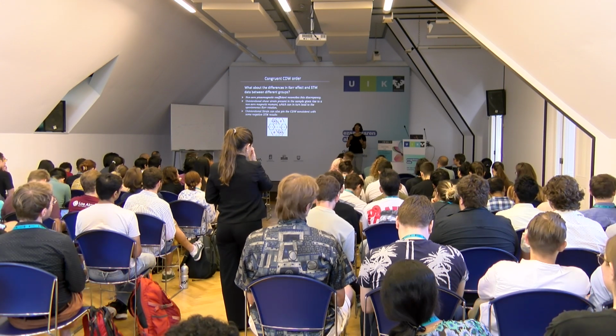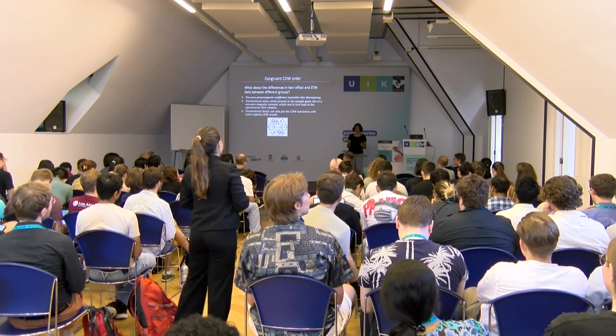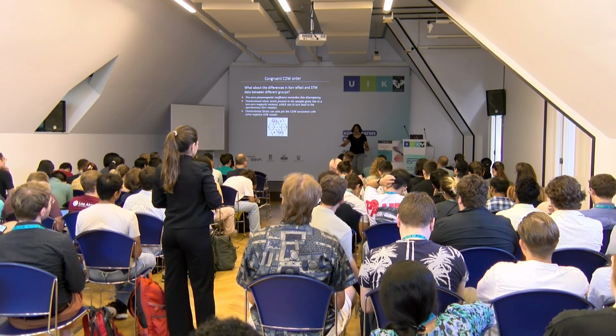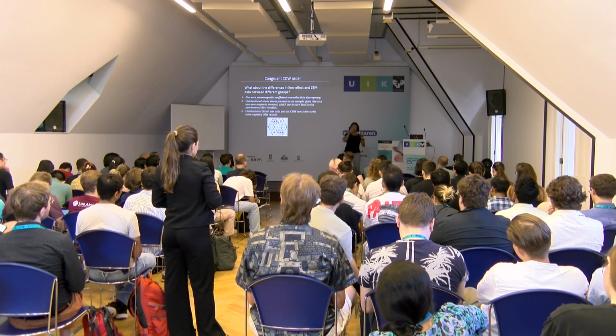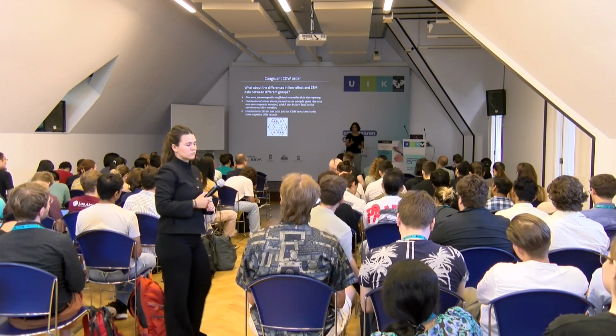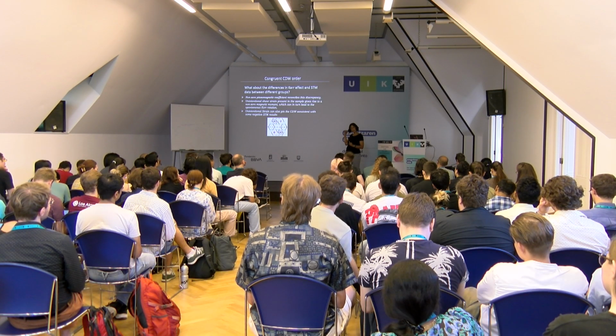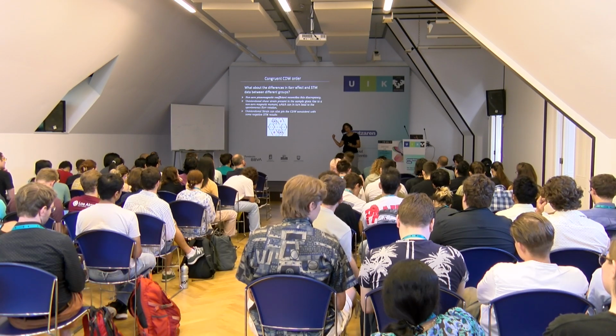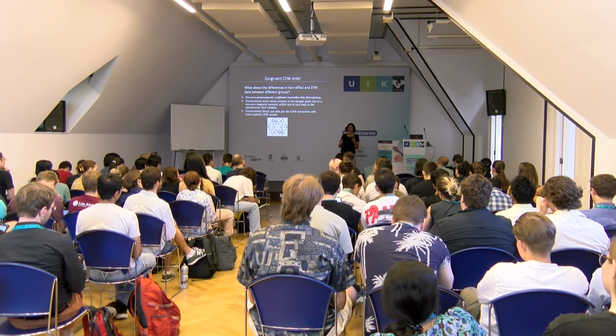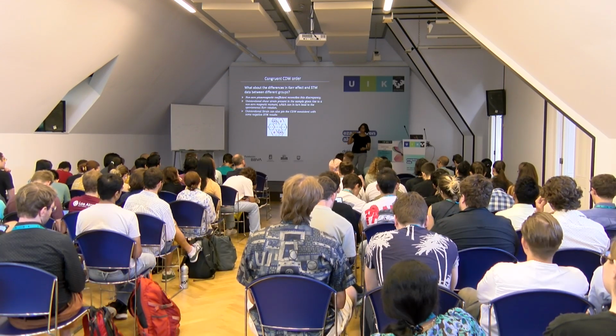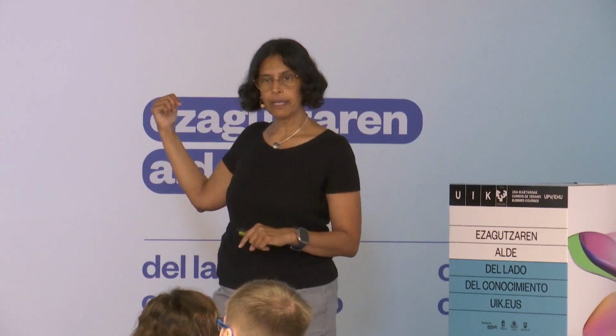The answer is yes. All I'm saying is that if you looked at a system with no strain, and the staggering that I'm talking about in 3 dimensions were not there, then in theory, all the CDW peaks should be the same intensity. However, in a magnetic field, you would still see the piezomagnetism. So in a magnetic field, suddenly the relative intensities of the peaks would be different. And then when you flip the field, you would flip that because of this piezomagnetism.